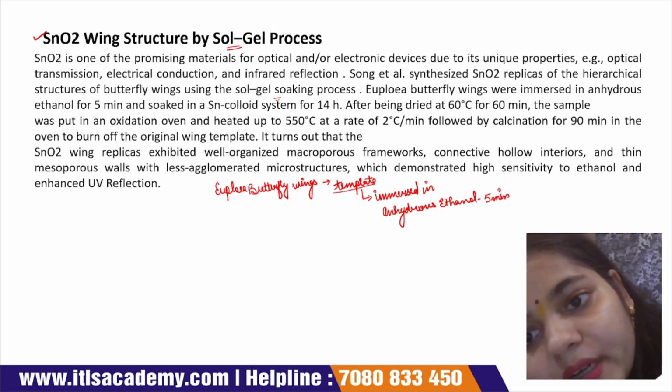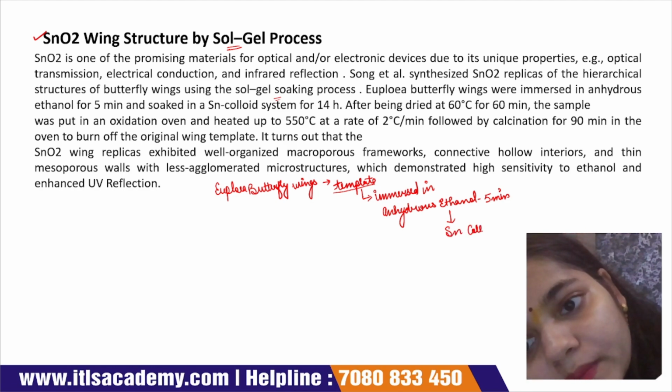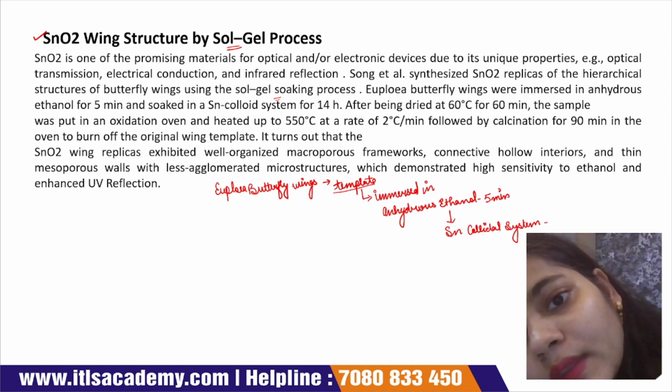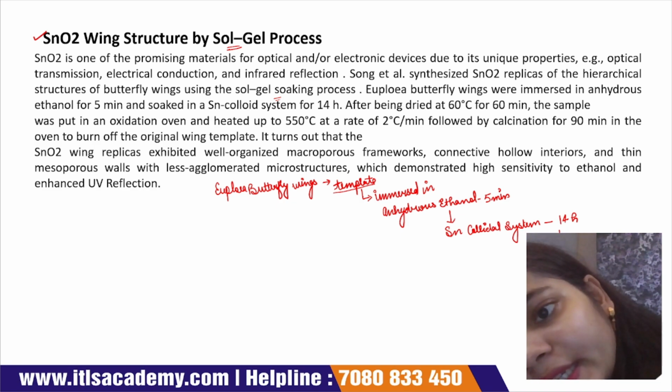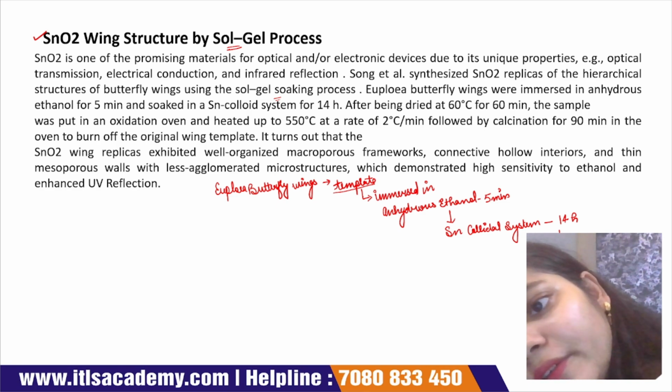After the 5 minutes, it will soak into the SnO2 colloidal system for 14 hours. After the 14 hours, it will be dried at 60 degrees centigrade for 1 hour.